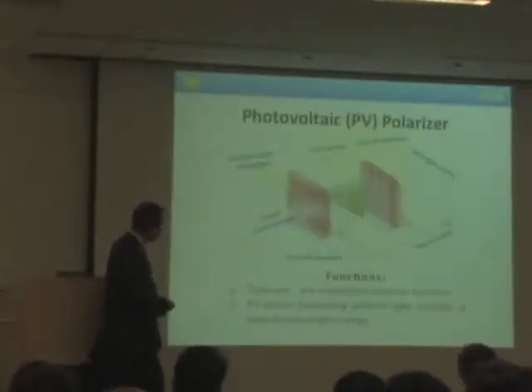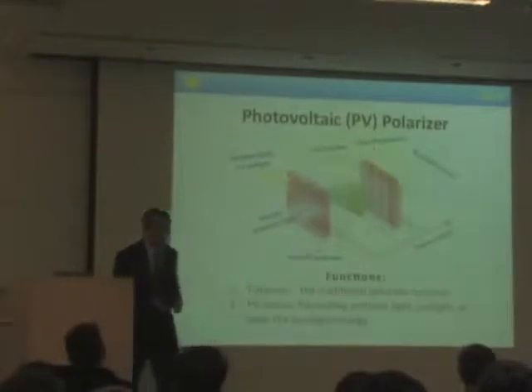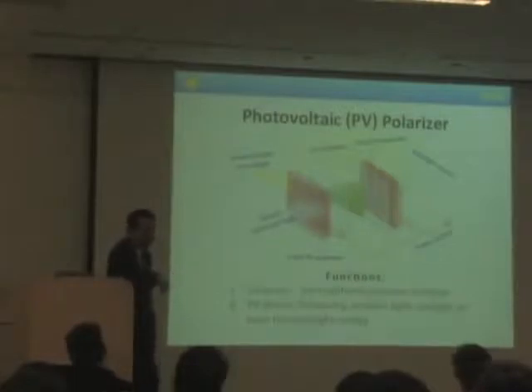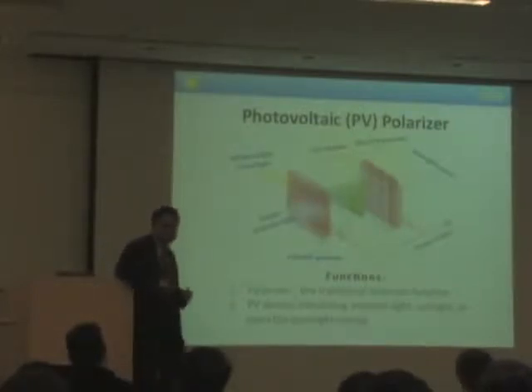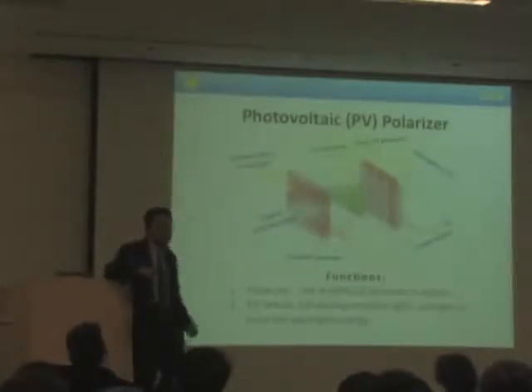What we have done here is use oriented P3HT to replace the polarizer. Not very good at this moment, but we demonstrate proof of concept. We want to use the polymer molecule to do the orientation. In fact, this idea of the oriented polymer was not new. When I was at UNIAX, Professor Heeger and Professor Wudl demonstrated it using MEH-PPV. It is another important invention by Fred, that they used polystyrene to stretch the polymer to study the photophysics of the polymer. Instead of doing that, we are using mechanical rubbing to do it.